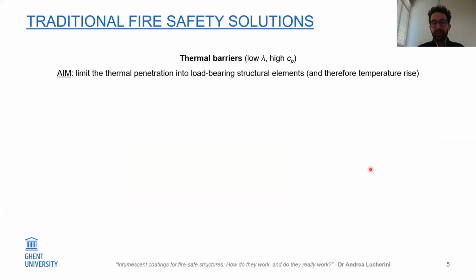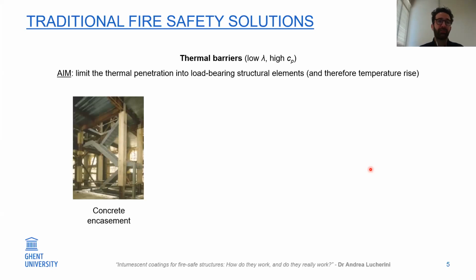So the common, traditional way to solve this is to use thermal barriers of different natures. They're usually characterized by low thermal conductivity or high specific heat, and their aim is to limit the thermal penetration into the load-bearing structural elements, therefore limiting the temperature rise of the structural elements and the structural substrate. Some traditional examples are concrete encasement, where you wrap the steel element, in this case the steel column, with concrete, which acts as an insulation material around the steel column.